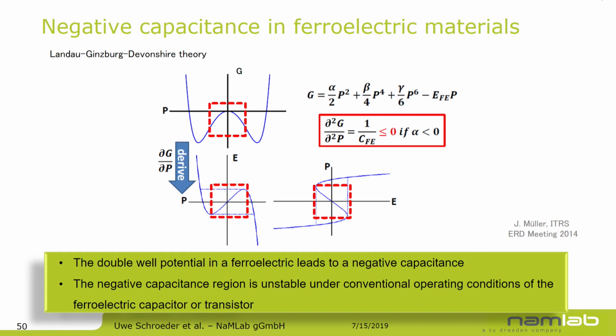Just to explain where the basic idea is coming from, if you think of the Landau theory, you would have, for the Gibbs free energy, this double well potential, and going from one polarization state to the other, you have to overcome this barrier. The important part would be this region where you cross the barrier. If you derive the structure, you would have this E versus polarization, the field versus polarization characteristics. You just flip E and P, and you get this known shape. And typically, looking at the structure, the slope of this curve would determine the capacitance of the material.